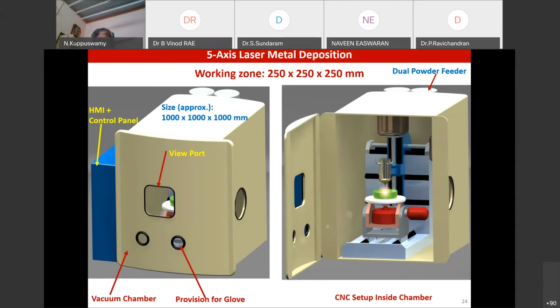Now, in the case of a powder bed, when you're reusing the powder, the oxygen in a normal atmosphere, they call it with argon. Okay, they use argon control, but then the EOS doesn't remove all the oxygen to start with. They don't evacuate to a very high degree. In an Arcam machine, they do it, not in an EOS machine. Therefore, the residual oxygen is quite high, even though they keep saying they're doing it in argon atmosphere.